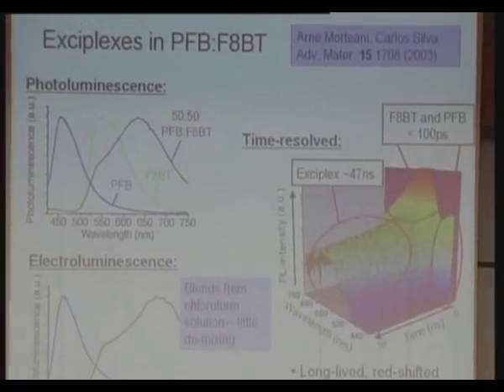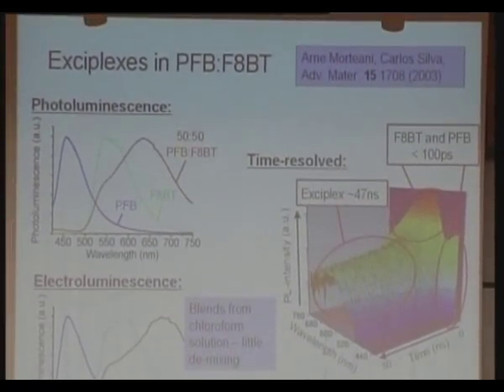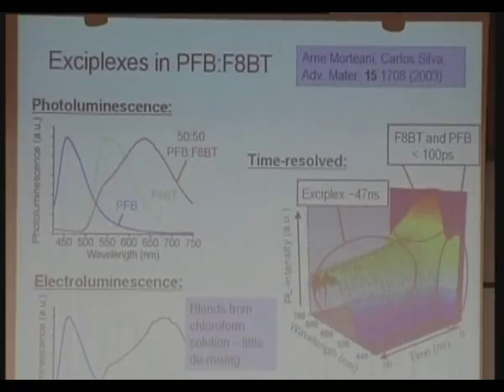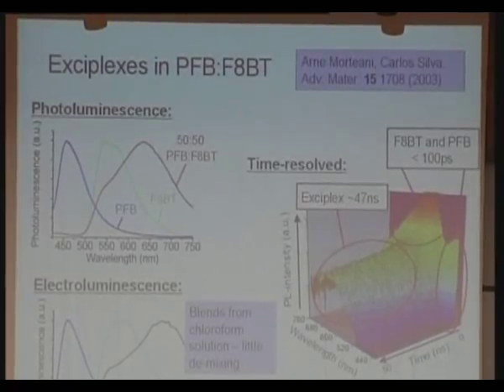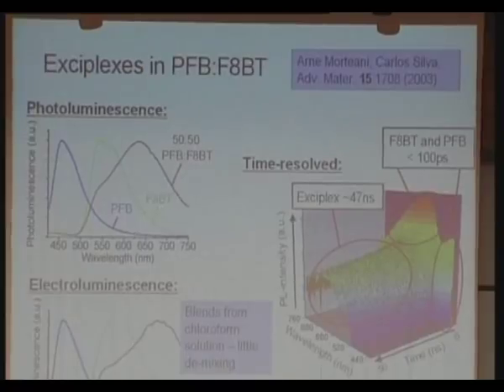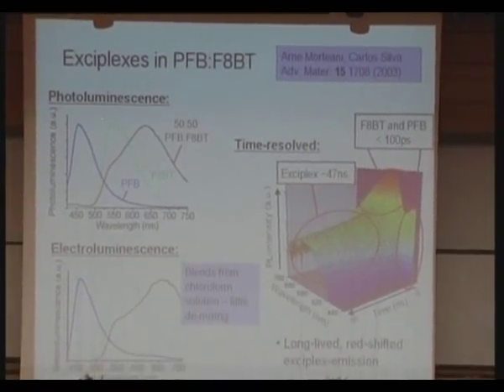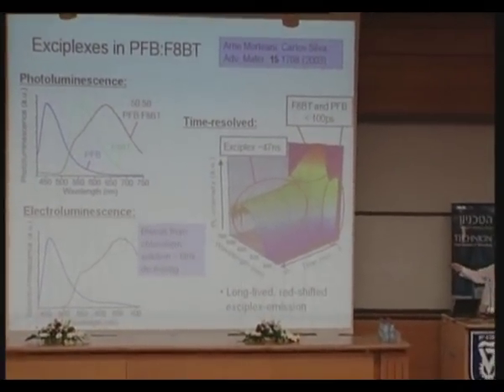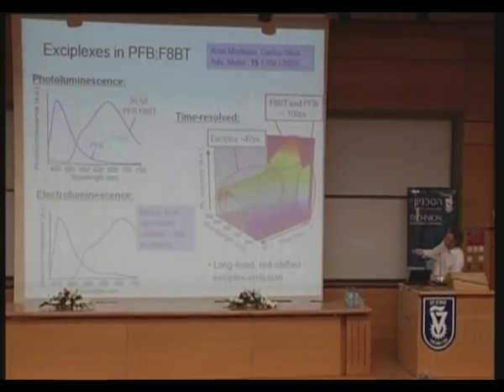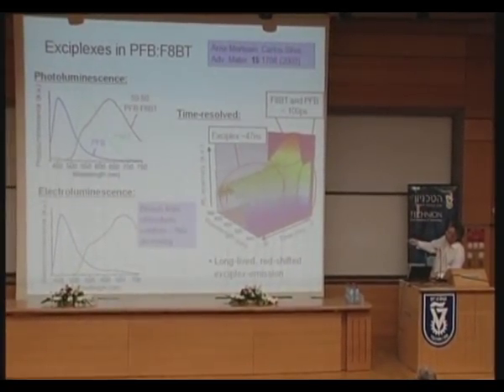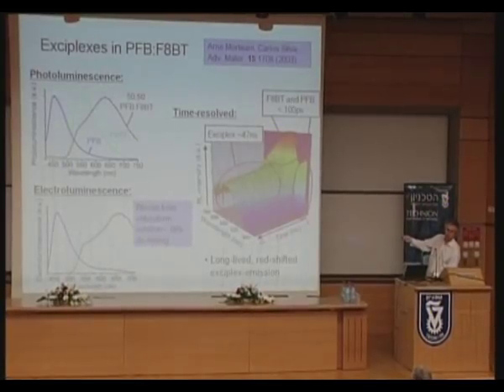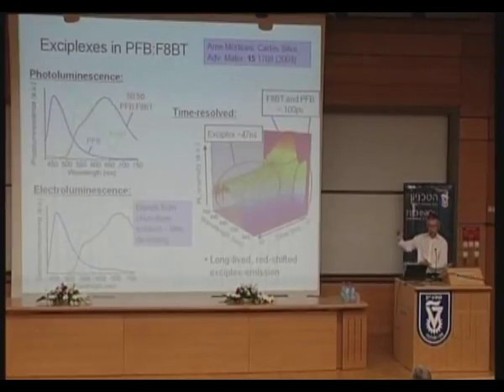So it's much slower. What is shown here are the luminescence spectra for the pure hole acceptor, the PFB here. It's a blue material. The peak emission is around 470 nanometers or thereabouts. The electron accepting polymer, F8BT, is sort of yellow green. Its emission is around 530 nanometers, but mix them together and we get red emission with a peak at about 630 nanometers. So that red emission is this across the heterojunction transition.